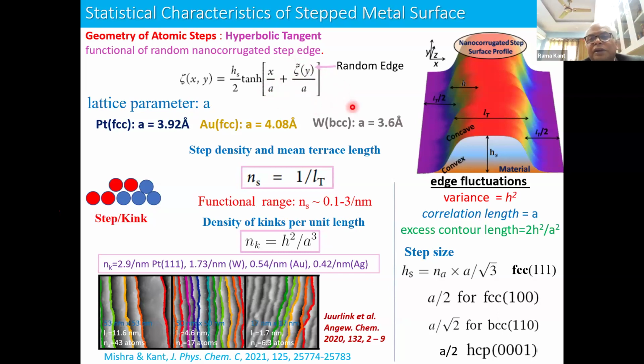So definitely we have taken it random, so we have to do certain averages before the theory becomes functional. We did all those things to account for that. The number of steps, which is one important parameter when you have a step, is inversely related to the average terrace width. And people do experiments by measuring this quantity and reporting the electron transfer kinetics. The functional range of these atomic steps, where atomic steps start influencing electron transfer kinetics, is 0.1 step per nanometer to 3 steps per nanometer. Beyond that you cannot pack, because then the terrace width is smaller than an atom. So that's the upper limit.